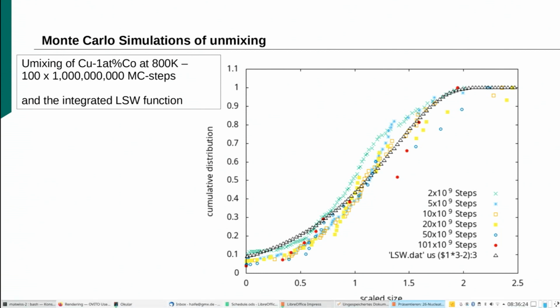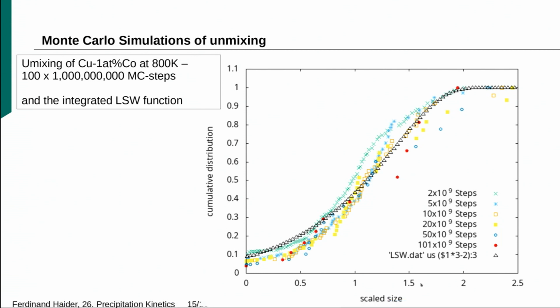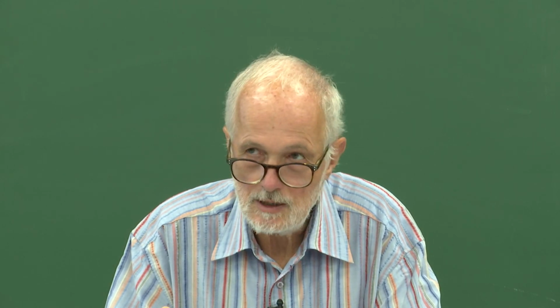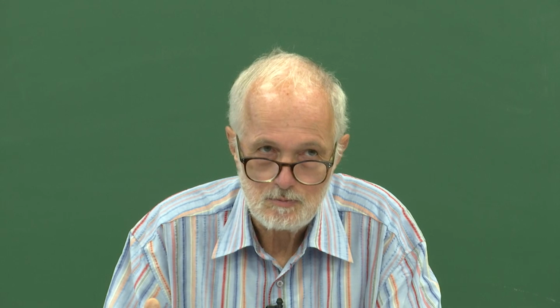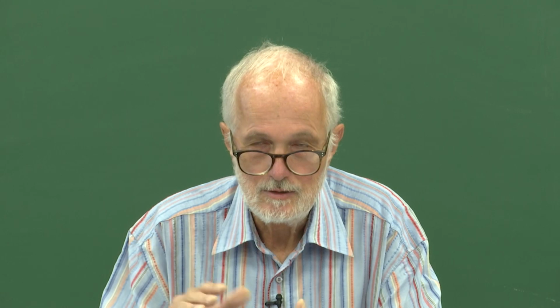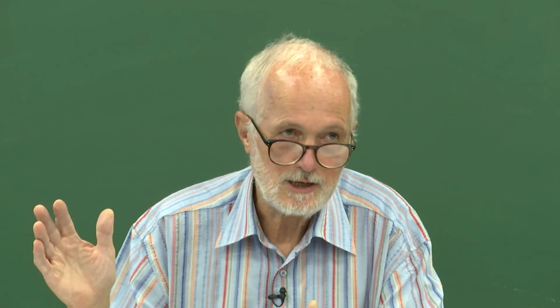So this is the classical picture of precipitation, distinguishing between these different phases, which is a bit arbitrary. This might be another reason why these things do not fit so well, or no, in principle not. Normally, under real conditions, of course, you don't have this distinction in particular between the nucleation phase and the growth phase. I mean, while nucleation still takes place, the growth already sets in. So this distinction, for sure, is rather artificial.